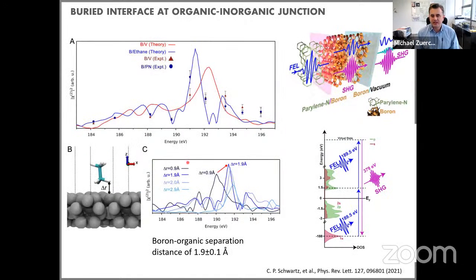Another system we studied is a buried surface, buried interface, I should say. In this experiment, we looked at the interface of boron and parylene. The experiment was done at FERMI in Italy. So we basically have parylene on boron. We come in with the FEL, we go resonant, and this is the other kind of energy scheme you can do. We go resonant with the FEL from boron 1s to a valence state, go through a virtual state, and we observe second harmonic at twice the photon energy, at 379 eV.